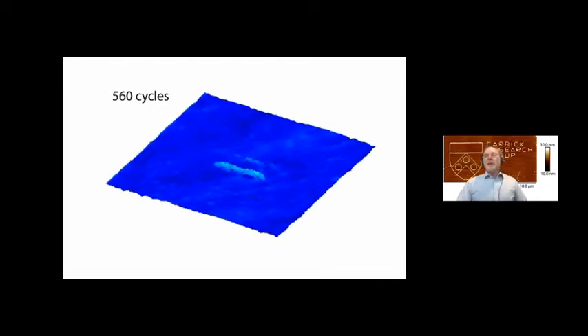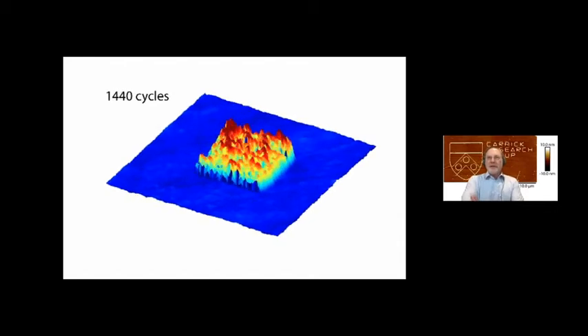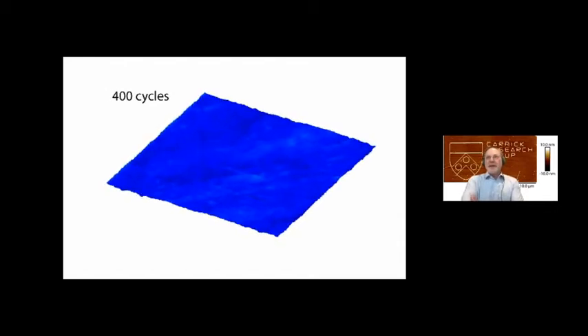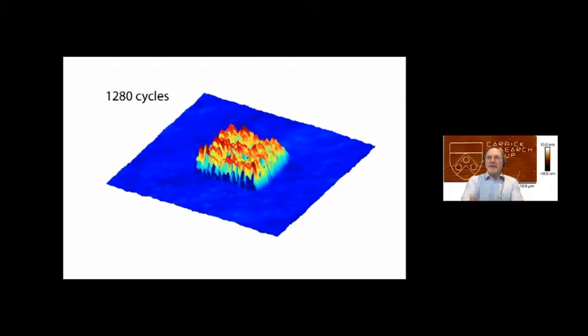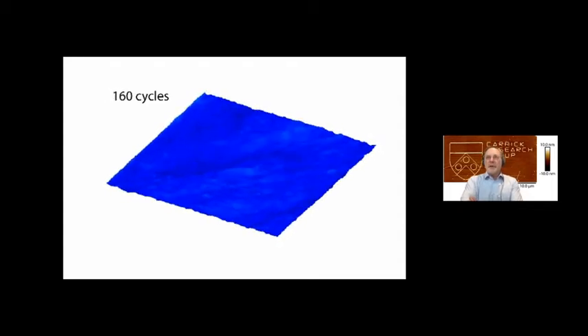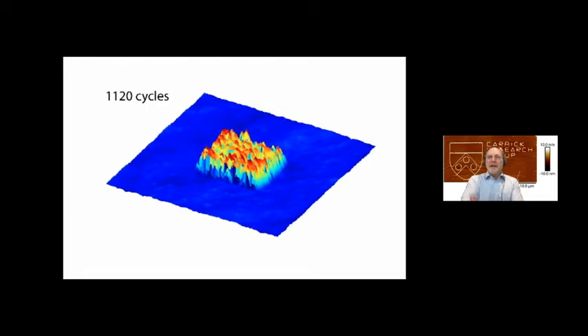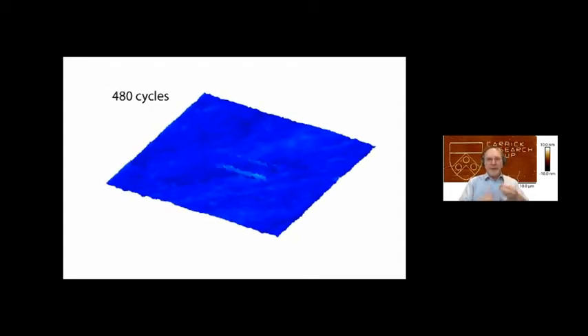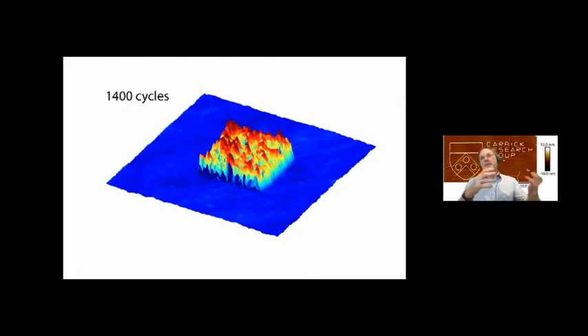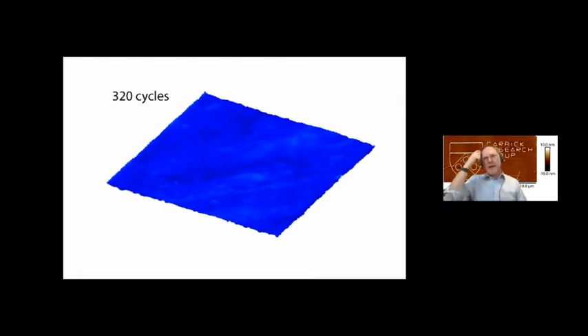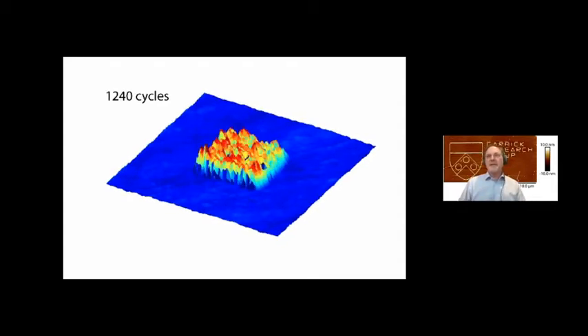Good. So it's repeating. You can see there's actually an induction period where nothing happens. Then eventually the nanoparticles start forming the film. They grow quite quickly, and then you see the growth levels off. You can see there's fluctuation. You can see this dancing of the topography. Both the average height of the film is fluctuating and the local height at different spots is fluctuating. So there is some exchange of nanoparticles, some attachment and removal at the top. But overall, that film remains.